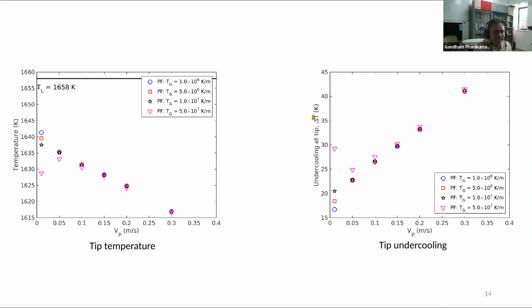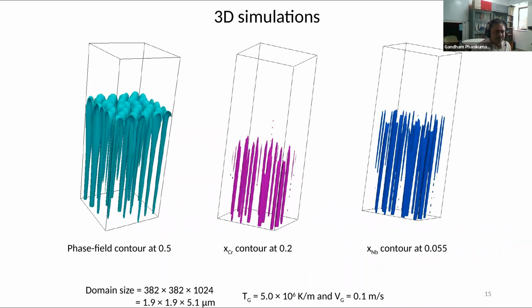For example, what is the driving force at the tip of a dendrite? What is the undercooling that we are facing, and what is the temperature of the tip, etc. All of that can be now calculated, because once you have a model that is calibrated, we can actually do many of these calculations, which are not possible experimentally. Now, experimentally measuring the compositions also is available, but it's not possible to locate it everywhere, because the electron beam, which calculates the composition in an SEM, has a particular volume from which the composition is being measured. So if you want to make a composition map, etc., it's very painful, and you can only do it in 2D. So if you want to see in 3D how the compositional variation is happening, phase field simulations can give you. So here is an example of the chromium composition contours and the niobium composition contours in a 3-dimensional representation that is entirely possible.